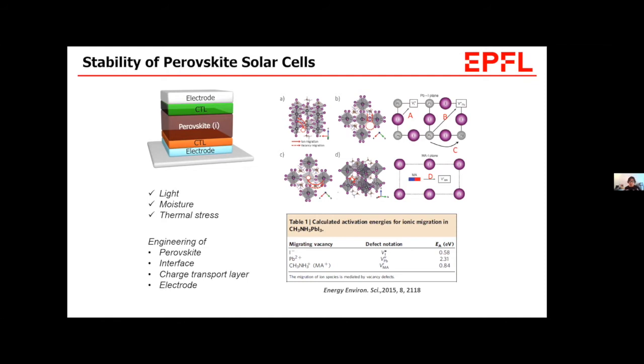For example, a solar cell, if you maintain maximum power point, has less than 1 volt. For LEDs, it will be much greater than 1 volt, like 4 volts. According to the electric field across the device, there will be much faster ion migration, and then the accumulation of these ions at the interface can degrade the interface very fast, which accelerates the device degradation again. So it can be one of the critical problems that leads to degradation during the operation of devices.